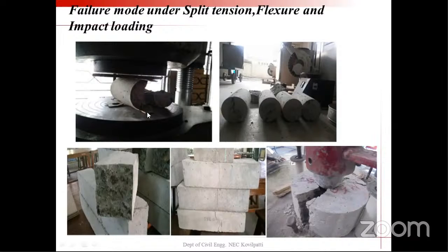So you can see the complete failure in case of control concrete. The specimen has been totally split into two. But these 4 specimens, even after testing, the integrity of the specimen is still maintained. Only a single crack has occurred along the specimens. And the bottom line diagram is the control concrete. And these 4 specimens have been tested as flexural beams, after flexure modulus of rupture testing. So still the specimen integrity is maintained, no complete collapse or catastrophic failure.